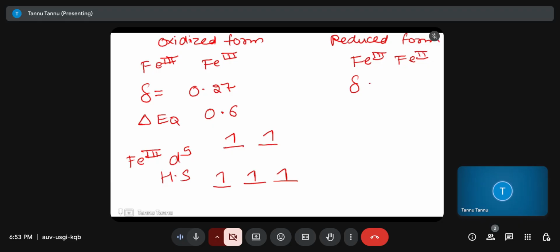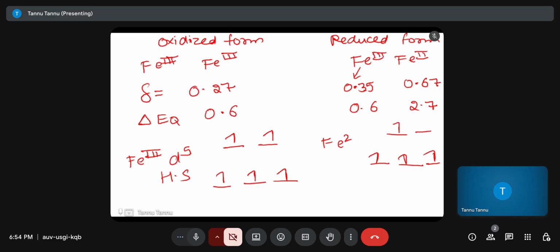and here the isomer shift is, there are two isomer shifts here. For Fe3 it is 0.35, for Fe2 it is 0.67, and the quadrupolar splitting is 0.6 and 2.7. Fe2 again, high spin. So here it is asymmetrically filled. So there is valence contribution, and you have non-zero electric field gradient.